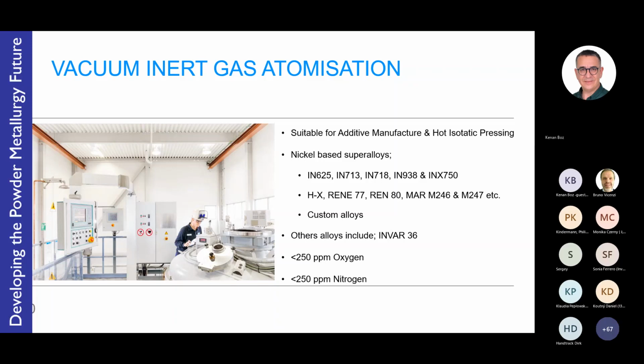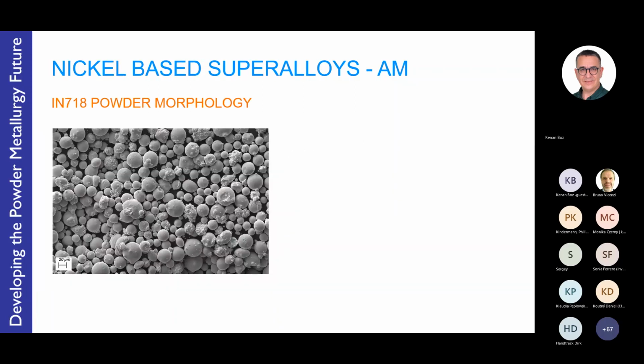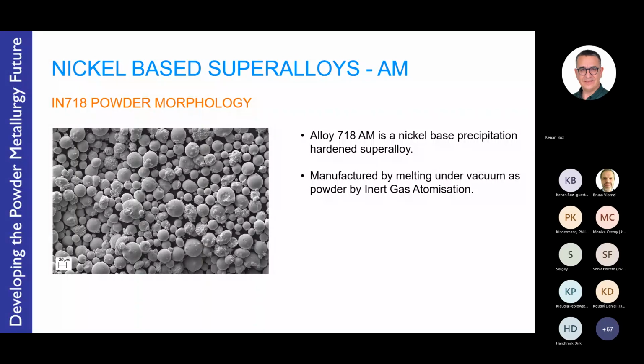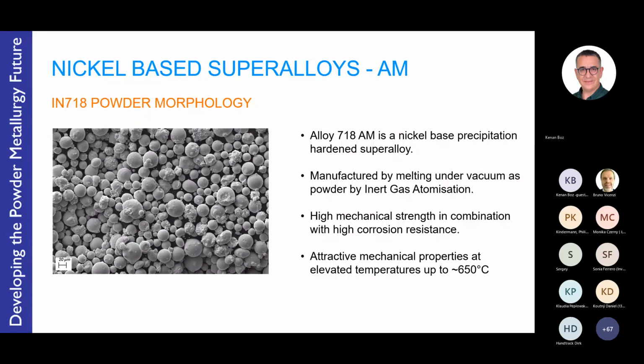And the advantage of melting in vacuum, of course, is low oxygen and low nitrogen levels. So taking one example of this, 718 powder, here you can see a typical morphology of vacuum inert gas atomized. It is a precipitation hardened superalloy. Melted under vacuum, then inert gas atomized. It has a combination of high strength and good corrosion resistance and can operate up to 650 degrees C.